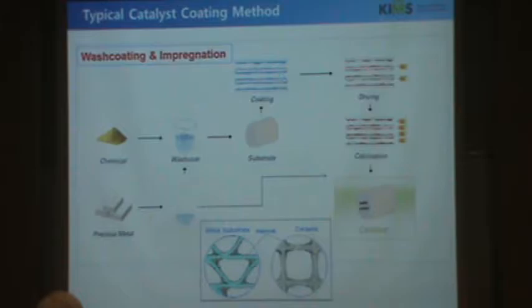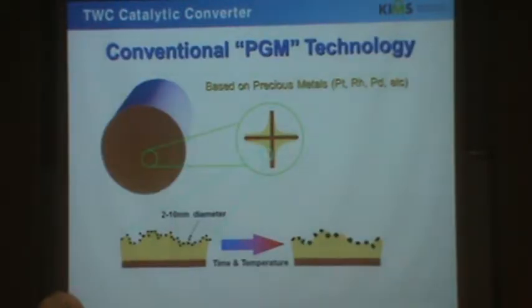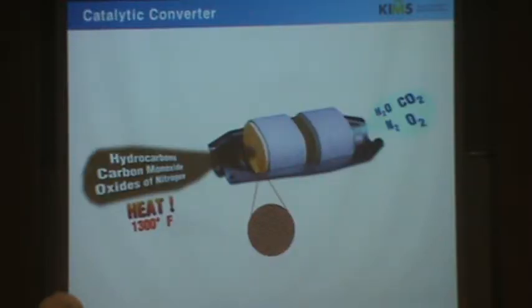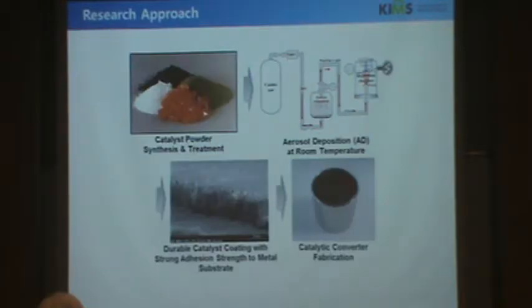This is a typical wash coating or impregnation technology for automobile or other catalyst applications. And this is a conventional monolith catalyst, the coated monolith having the nano-sized catalyst inside. And this is a typical TWC catalyst. Now I'm going to talk about a special, unusual technique for coating. It can be called powder spray coating. We didn't use a wet solution. We use a solid powder, and we directly coat it on the substrate. And this was a typical SEM picture of the coated catalyst. I will show more later.